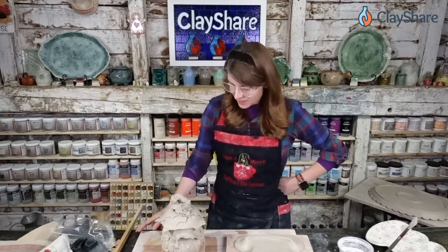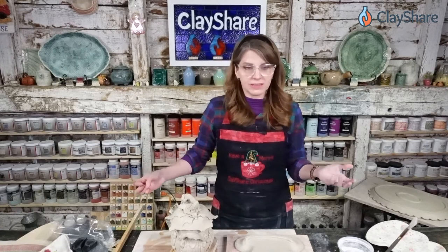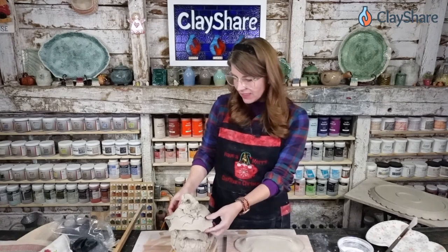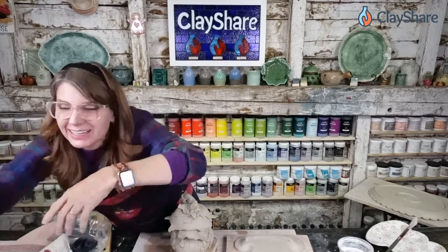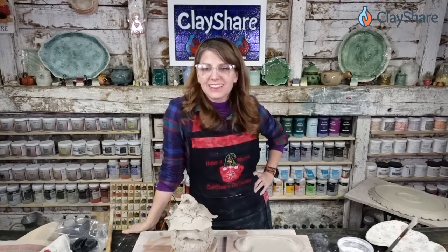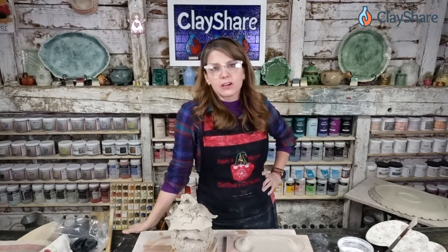For glazing these pieces: use a zinc-free glaze. Zinc can react to underglaze — it can erode it, change the color, or cause crazing. Also, don't glaze too thickly or you can get pulling away. I'm going to use Speedball Stoneware Glaze, which is a cone 5-6 zinc-free glaze. It doesn't say zinc-free on the package but it is — I have confirmation from Speedball, and many others have gotten the same answer.